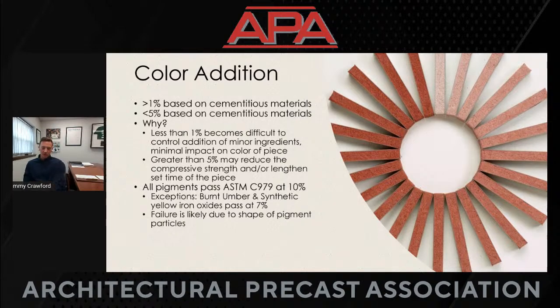All pigments pass C979 at 10%, except for burnt umber and synthetic yellow iron oxide, which pass at 7%. I'm not going to get too much into this. This is kind of a color nerd thing, but the shape of the color particle, synthetic yellow iron oxide, is like a needle-shaped particle, and that is believed to be the reason why synthetic yellow doesn't pass at a higher percent addition rate.